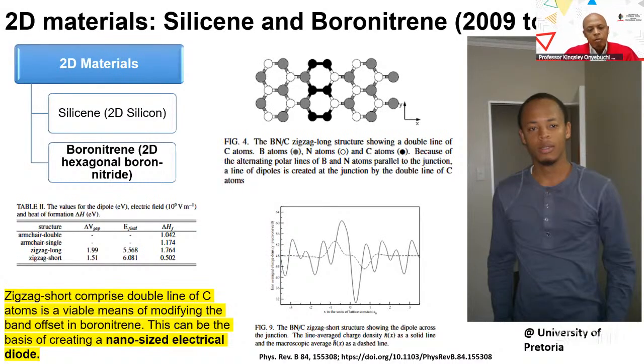And interestingly, we evaluated the boron nitride and we're like, okay, it still has a large band gap. And the idea of the band gap is a material is defined as either semiconductor or insulator based on the band gap, whether it has a large band gap or a small band gap, this will determine the property. And based on this, we're like, okay, can we further evaluate this system? So we now decided, okay, can we introduce a line of carbon inside there? So if you look at these black dots here, these are the line of carbon.